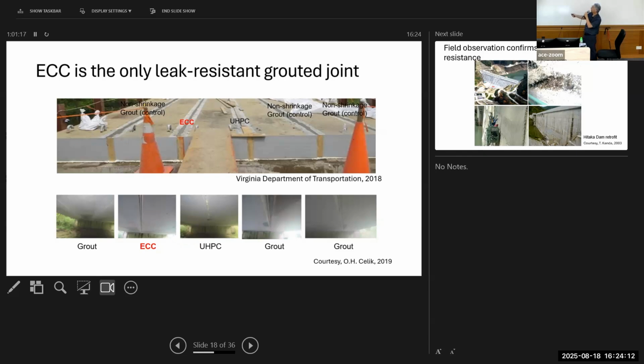And they adopted two new materials, UHPC and ECC, in the other two joints. So this whole assembly was then exposed to the natural environment. And what is interesting is that they monitor leakage of water from the underside of this bridge deck. And the ECC was the only one, they told me, that there was no leakage at all.